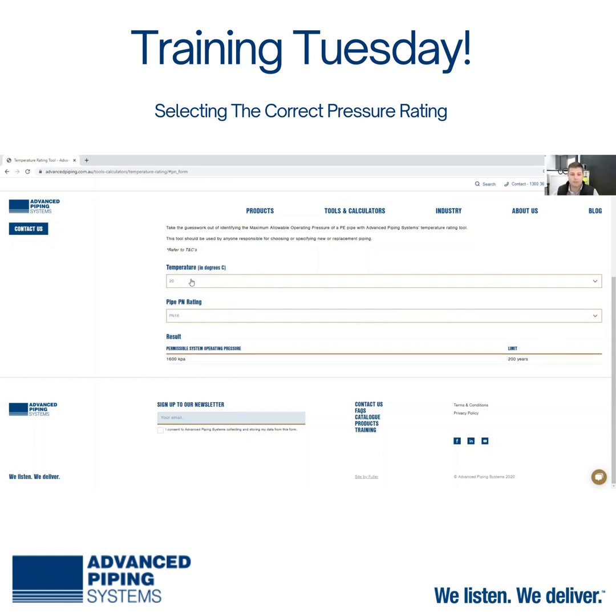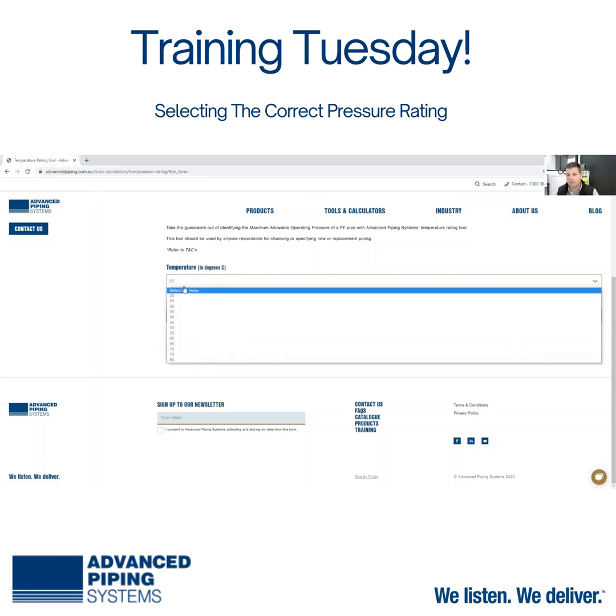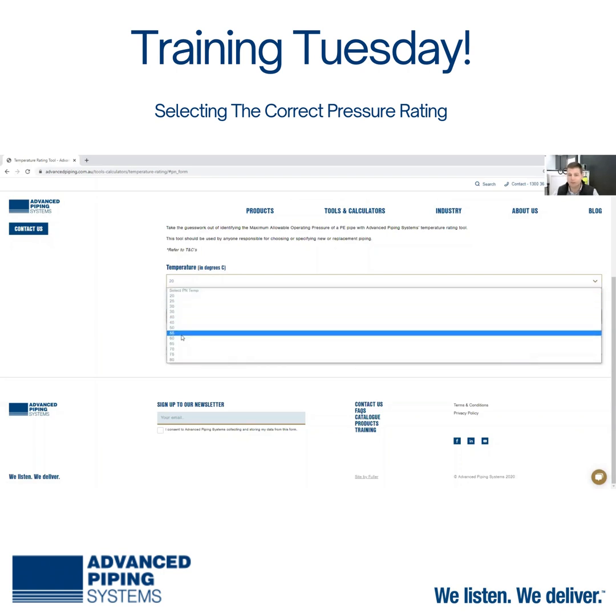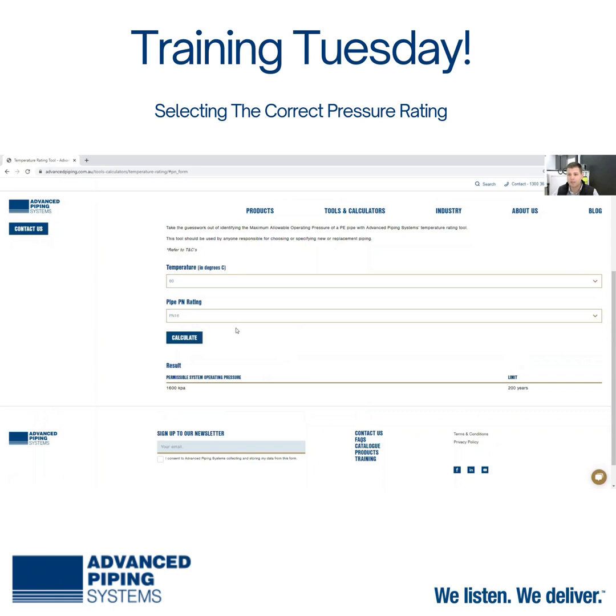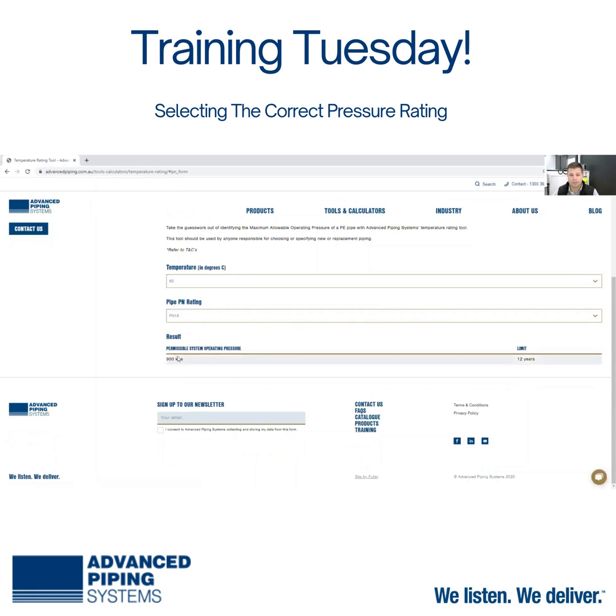So if we increase this temperature, say if we're sitting out in the sun and the pipeline could get up to 60 degrees in the middle of the desert somewhere, we recalculate this, we can see quickly that the permissible system operating pressure has dropped to 900 kPa. Now that's because polyethylene is a thermoplastic, and obviously when it gets softer, the strength of that material reduces.